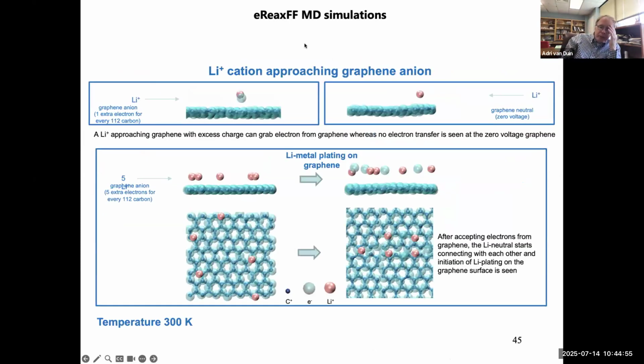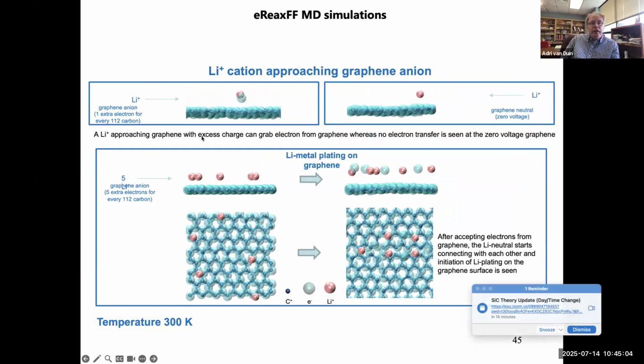And so now we can actually start doing simulations to look at what really happens in a battery. We can have, for example, multiple lithium atoms. When the lithium atoms initially are ions, they essentially don't interact with each other, so they stay as far away from each other as they can. But when they start grabbing electrons, they become neutral lithium, and the neutral lithium can start making lithium metal. And this is reversible. I can now, for example, also reverse this. I can take electrons out of my graphite. The graphite will then start stealing electrons back from the lithium. The lithium becomes lithium plus, and it will start dissolving in the electrolyte. So you can really now do real battery cycling at the reactive level.